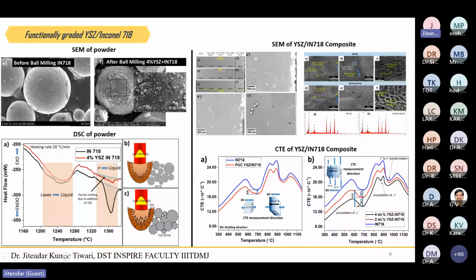Okay, so some SEM. The main finding of this particular work is that after the addition of yttria stabilized zirconia, the coefficient of thermal expansion is slowly decreasing. So we have tested this material with the dilatometer, and the results suggest that after addition of yttria stabilized zirconia, the functionally graded Inconel 718 can really accommodate the thermal mismatch. So we can target this material, and maybe in future we can plan to use this material somewhere in the gas turbine engine.